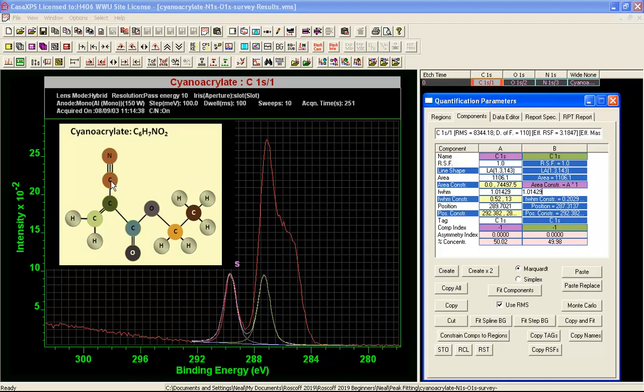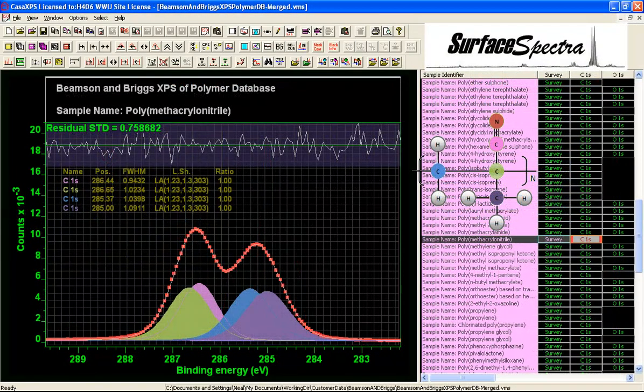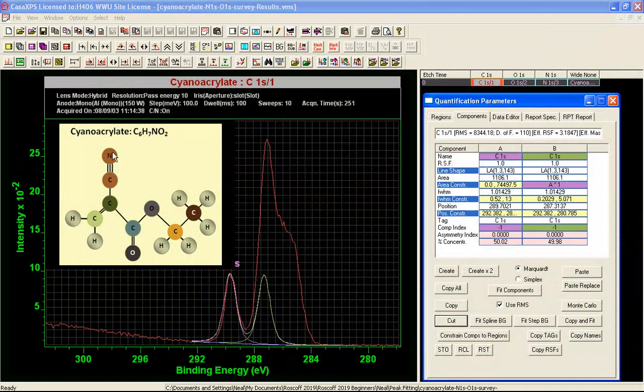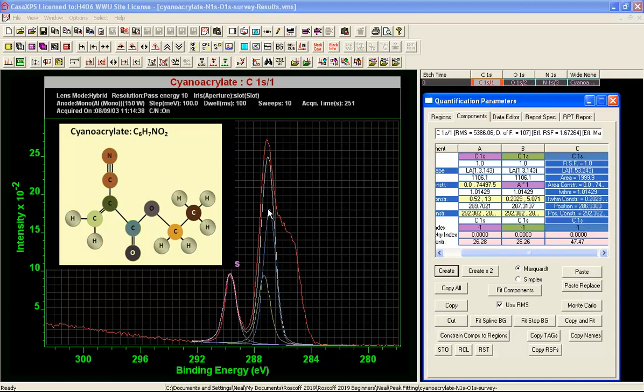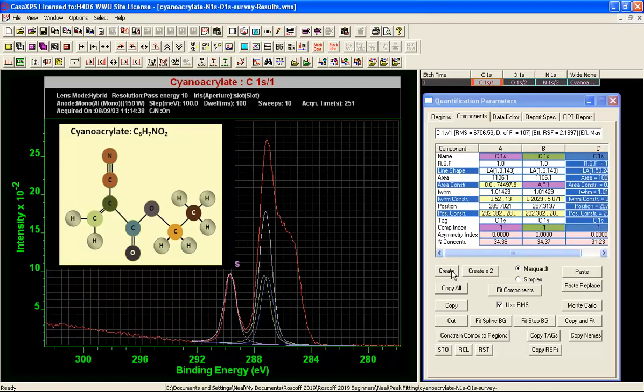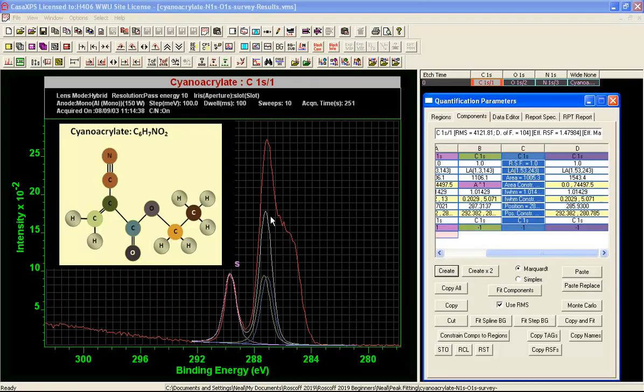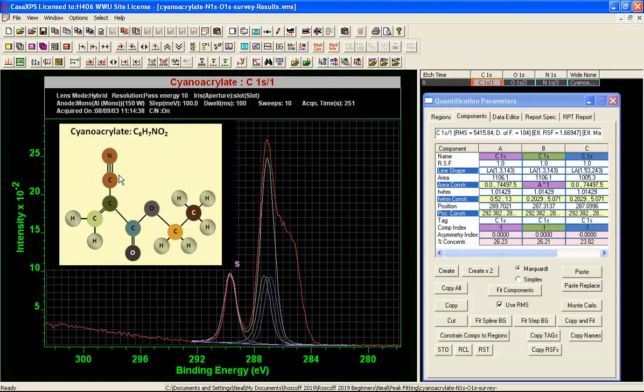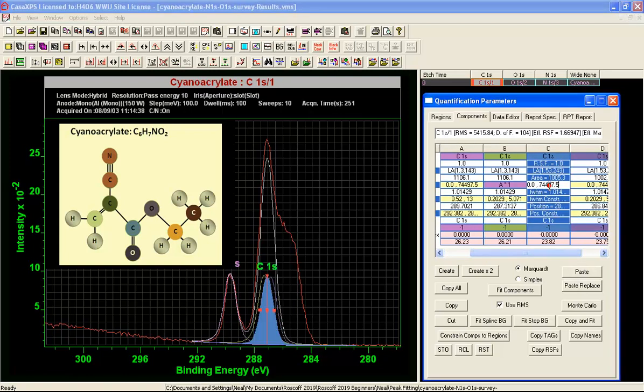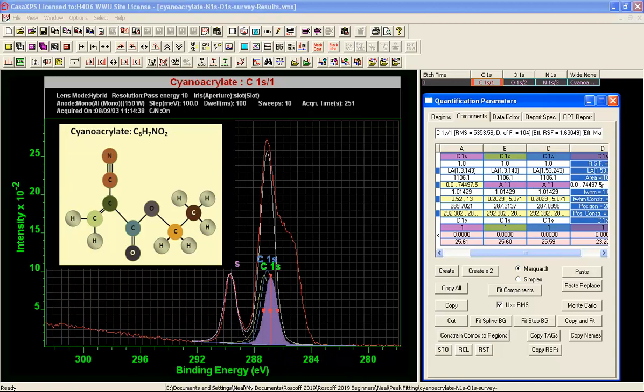We've got nitrogen triple bonded to carbon which is single bonded to carbon again. And from similar materials with this type of structure in the Beamson and Briggs polymer database, they introduce two peaks that are very close in binding energy for this type of structure. And since Beamson and Briggs have two peaks that are close in binding energy, we'll place two peaks here with the same area and we'll represent this structure here by these two peaks. And again we can say that they ought to have the same intensity as the other peaks that would belong to this structure. So I'm entering A star 1 for all of these. So these all have the same area.